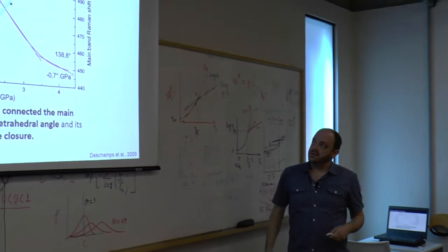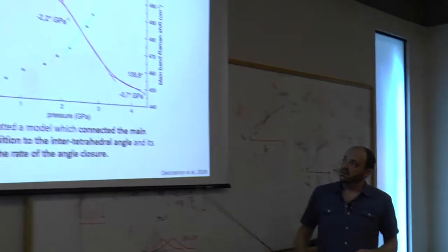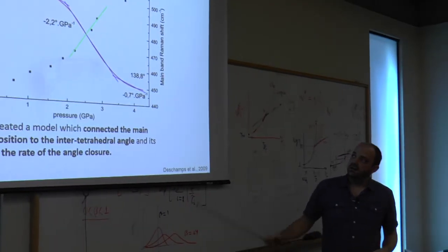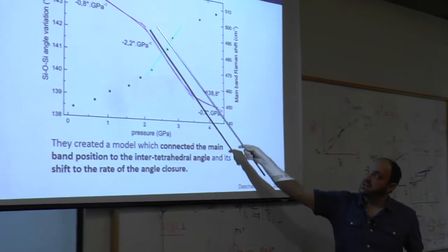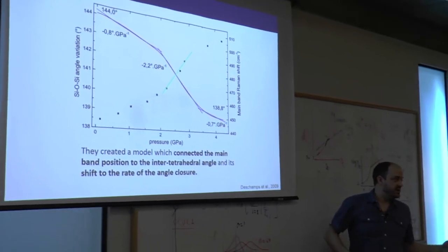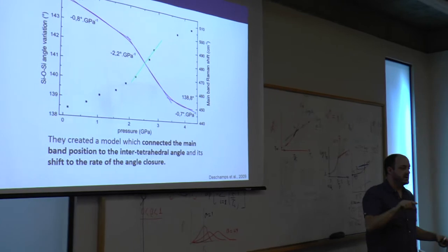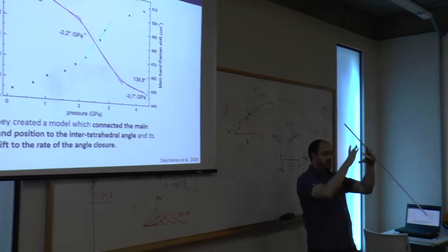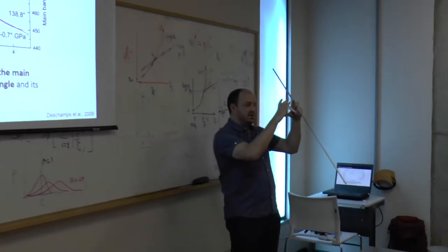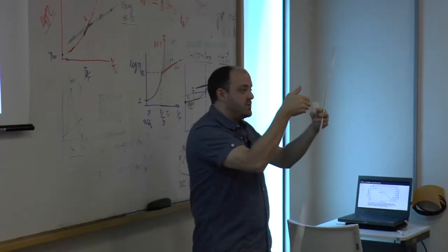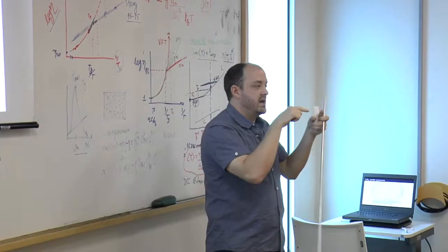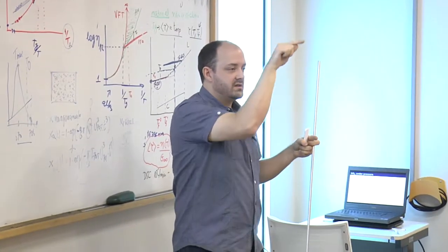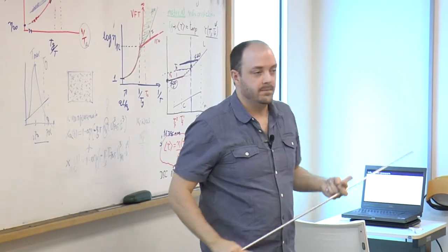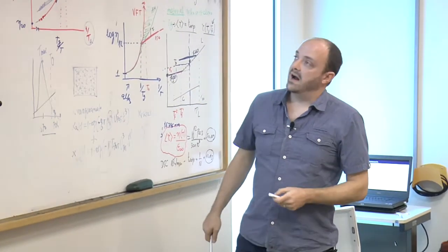The interpretation for this has actually been added to recently, and they now strongly suggest that this is related to an alpha-beta transition. So you have 6-member rings. If they're nice and wide, then as you increase the pressure, 2 of the tetrahedra will swing inside, and they kink. So you get sort of almost a figure 8, but of course there's no bond in the middle. And that's what's happening in this case.